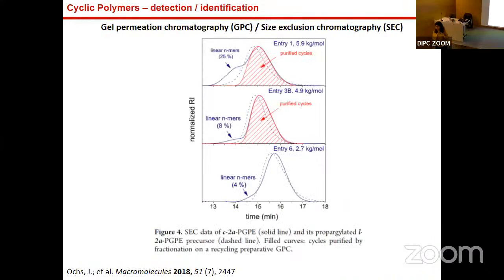GPC, this is another technique that we use to identify cyclic polymers, as I said before, because they show smaller hydrodynamic volume. They are smaller. This is an example of Jordan in some recent work we did. This dashed line is a linear precursor. Then we obtain the cyclic polymer, which is shifted. But as you can see, we have a shoulder here. This is very typically found in cyclic polymers when you use this ring closure approach. And this decreases with the decrease of the molecular weight, because the end groups find each other more easily.